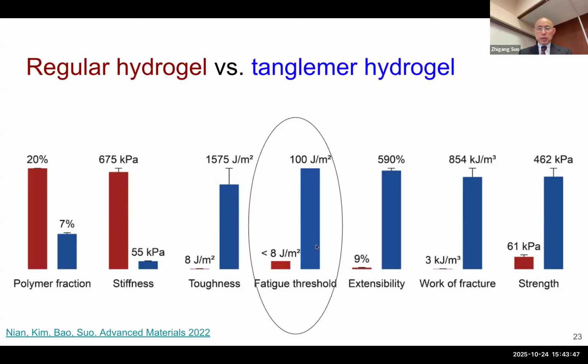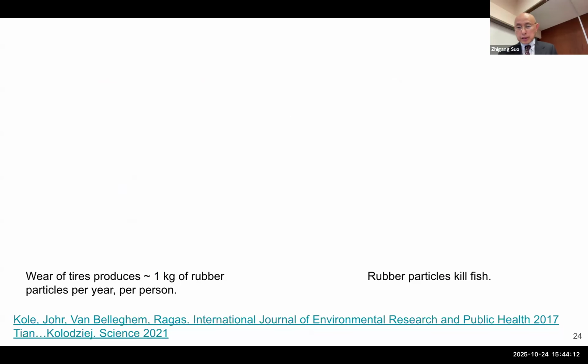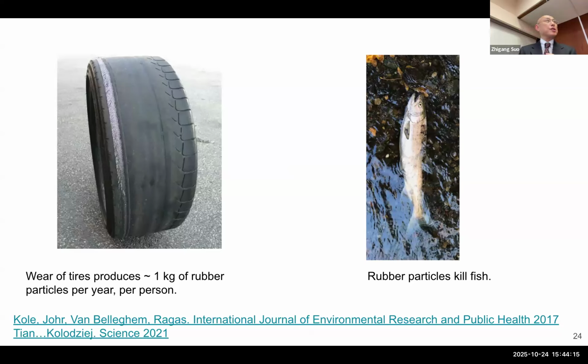Now the numbers, there are lots of numbers we compare. In our comparison, we make the blue material one, the red material another. This is the traditional material. The fatigue threshold is, as I said, very low, 8 joules per meter squared, and this Tanglemer is 100 joules per meter squared. It's real when you do this. All right, so then we get more ambitious. What is the most impact we can make with this idea? We decided it must be tire.